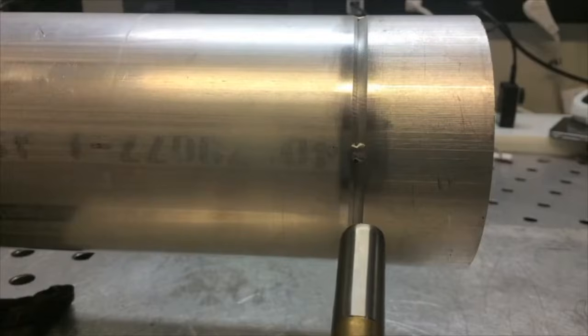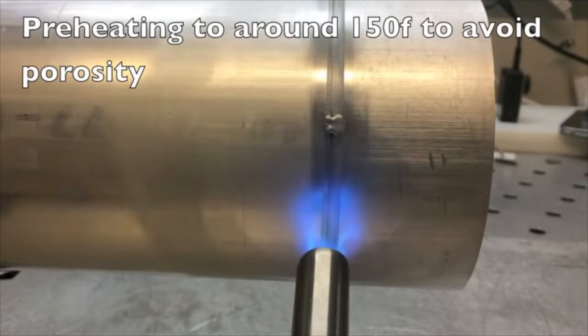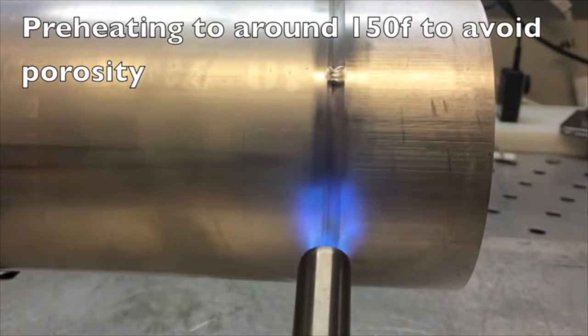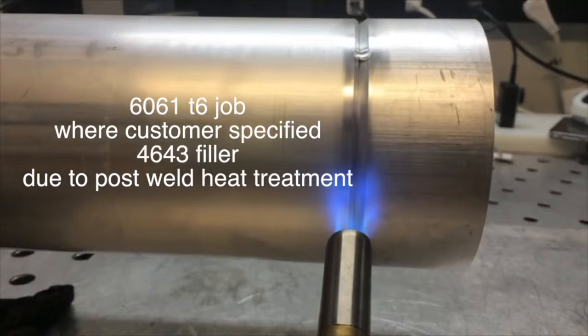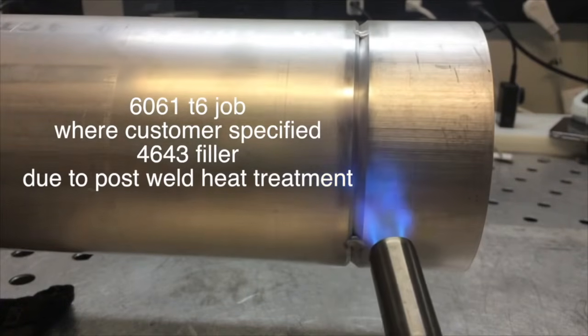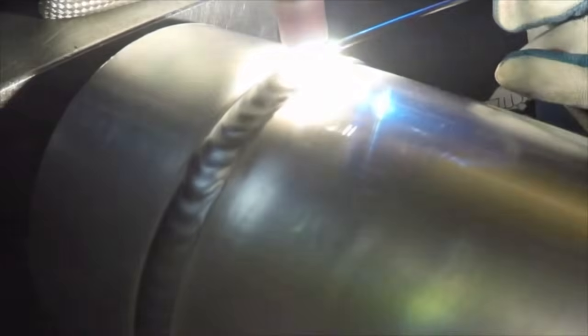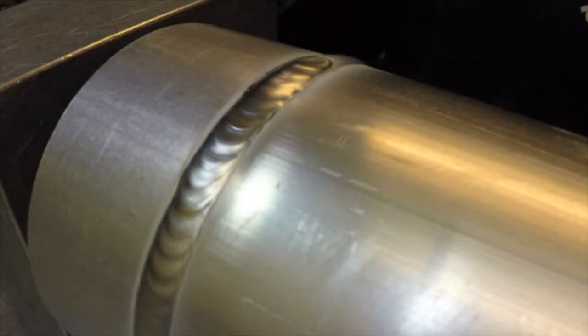4043 and 5356 aluminum filler metals cannot be strengthened much at all by heat treat. Other filler metals are needed when a post-weld strengthening heat treatment is called for. So here's an example of a 6061 hydraulic tube where 4643 filler metal was specified by the customer so that this part could be heat treated and the weld could be strengthened just like the base metal. Doesn't really help to strengthen the base metal if the weld is the weak point. So in this case, again, 4643 filler metal was used, specified by the customer.